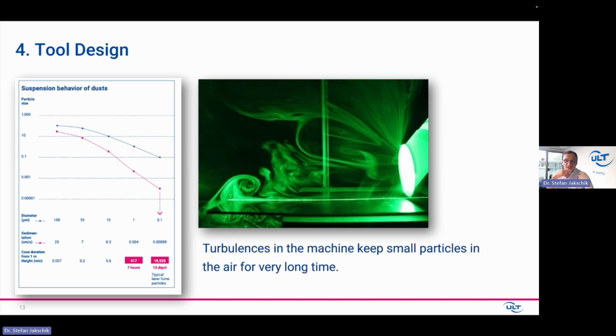Essentially, you have them always in the air. A particle of 100 nanometer will stay 14 days, or 30 days here, without any interruption before it comes down to the surface. But in a machine, you always have turbulences, so these small particles are always in the air. And so it is very important to suck them into a suction element as fast and as completely as possible.